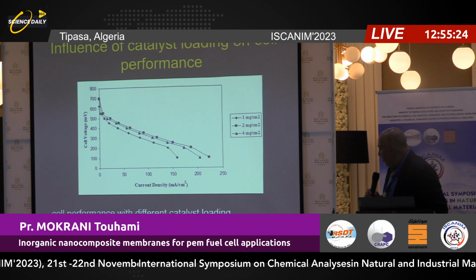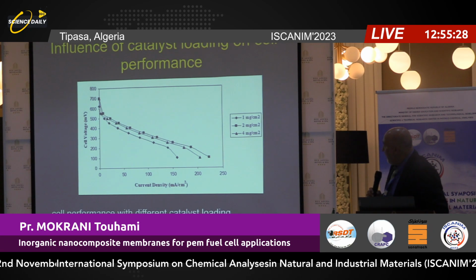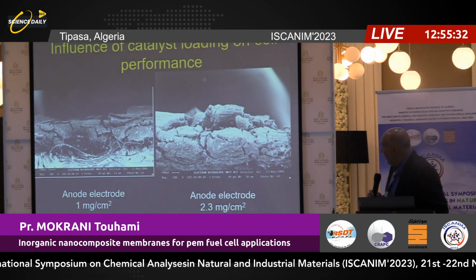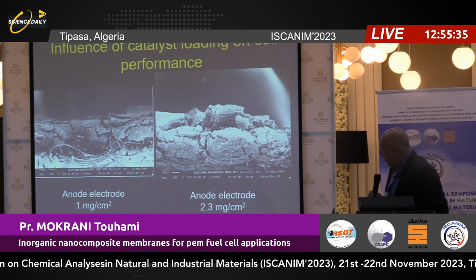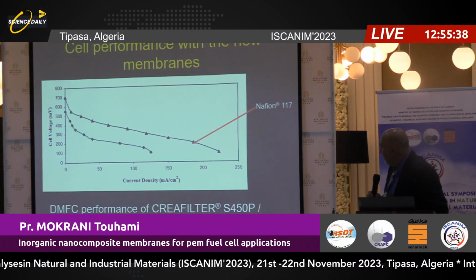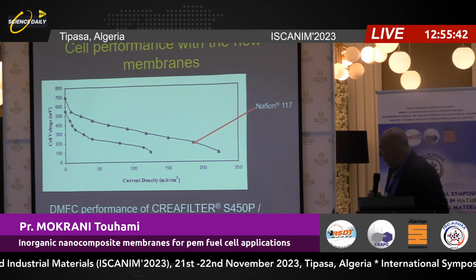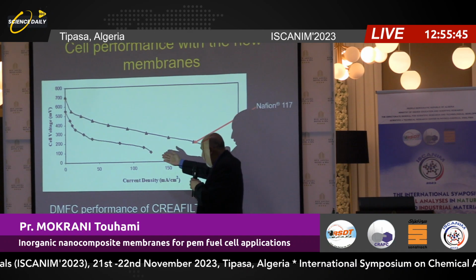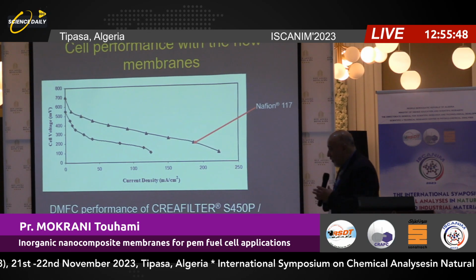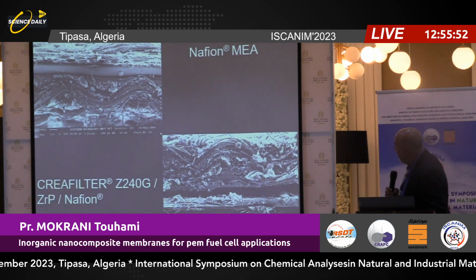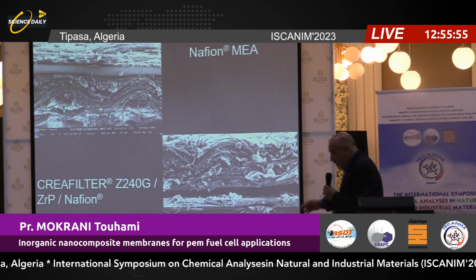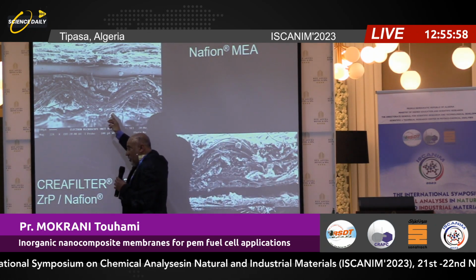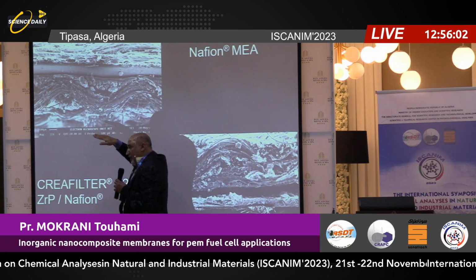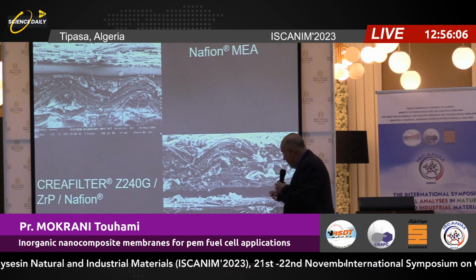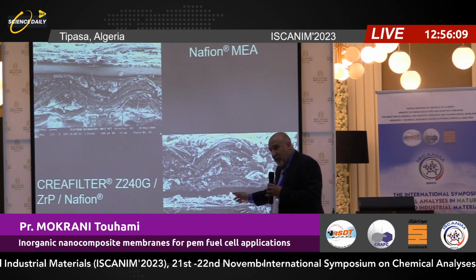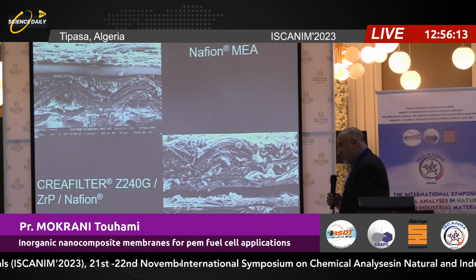You see, this one is where we tried to see the impact of catalyst loading on the cell. This one, we took pictures of the electrode. Here we compare with Nafion, and our performance is less. This one is the reference, and our performance is less. There are many reasons for that, but the most important one is this one. This is the MEA I am talking about. You can see it's layer after layer after layer. And here there is a big problem. We have delamination. If you have delamination, you don't have a good MEA.